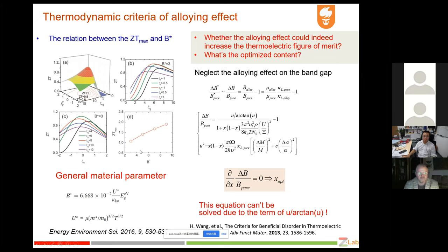In my previous work, we showed that the peak ZT of a system in a dual space, the temperature and the carrier concentration, is related to a general material parameter we call B star. This B star is defined by the weighted mobility, the band gap and the lattice thermal conductivity. Now, if we look at the alloy effect on the band gap, the benefits of the alloying effect will be reduced to this change of delta B.